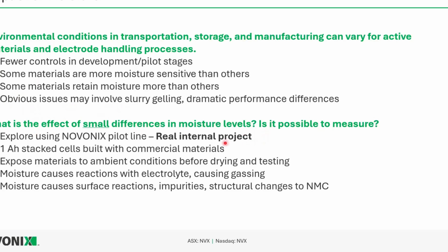So this is actually a real internal project that's ongoing right now. All the data I'm about to show is actually hot off the presses, analyzing these in Voltaiq and pulling them into this PowerPoint just this week. So we did this with 1 amp hour stack cells on our pilot line with commercial materials. And then I'll talk about how these materials went through their manufacturing. And we know that moisture within cells can cause reactions with electrolyte, cause gassing, and it can cause surface reactions and impurities, structural changes to NMC cathodes.